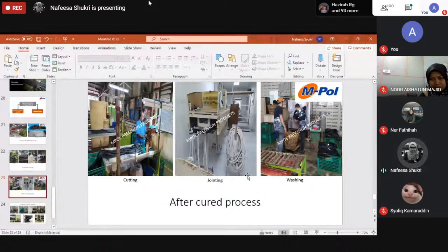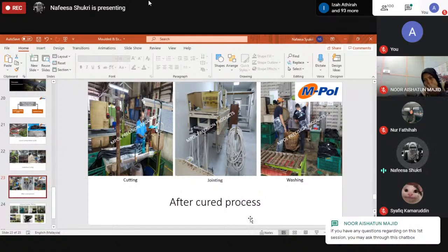We also have a washing process. Basically, washing is for the LCM extrusion method. When the rubber is immersed in the oil bath, the oil will attach to the surface of the rubber tubing. So we need to remove the oil from the rubber surface. We have a washing process. So these are the after-cure processes in Ampol: cutting, jointing, and washing.